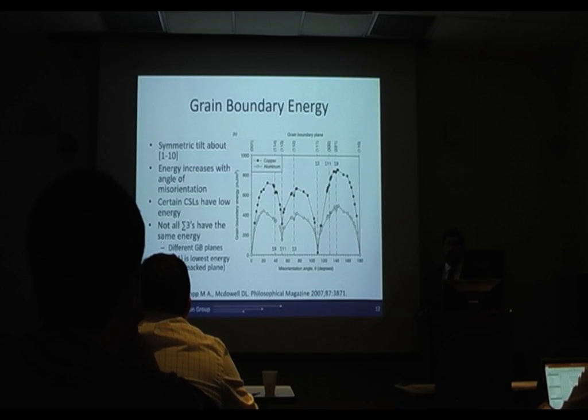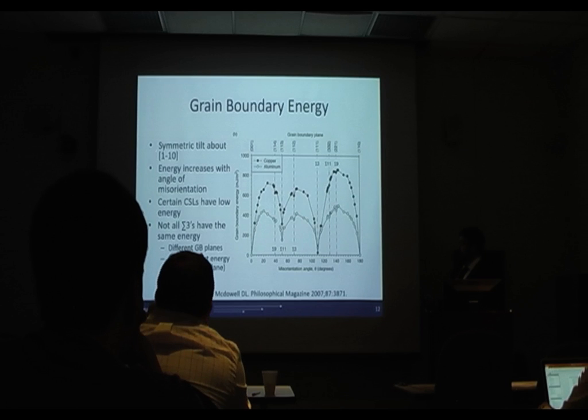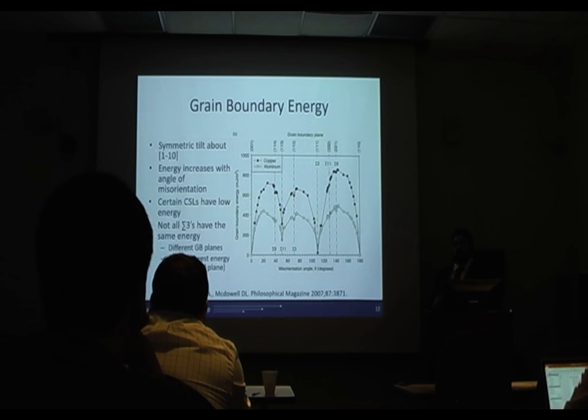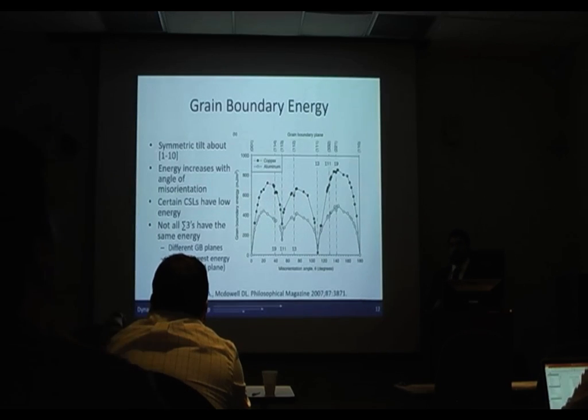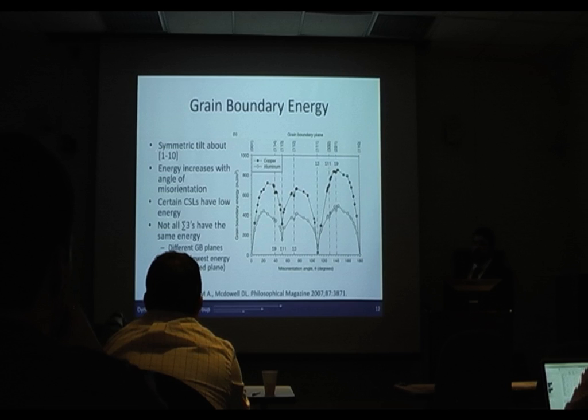Again, not all of them are the same. Even for the same sigma number, you can see that there's a small cusp for the sigma 3, and then a much deeper cusp for the sigma 3. And this is related to the grain boundary plane. So the sigma notation just tells you how the two lattices are related. It doesn't talk about that grain boundary plane at all. And depending on how the two crystals meet up, that will determine how many of those coincident sites are actually on that grain boundary plane. And the deepest cusp there for the sigma 3, as you can see at the top there, terminates on the 111 plane.